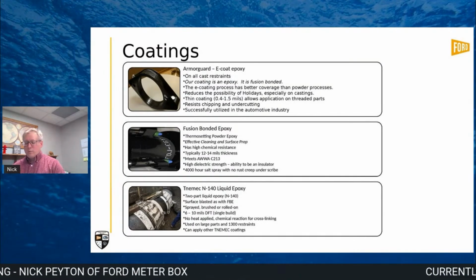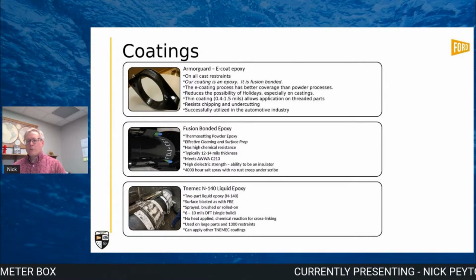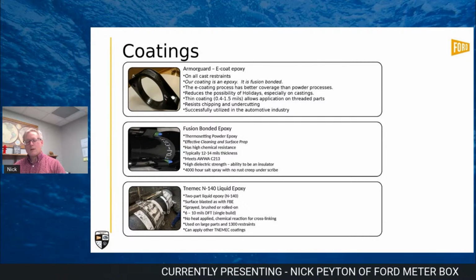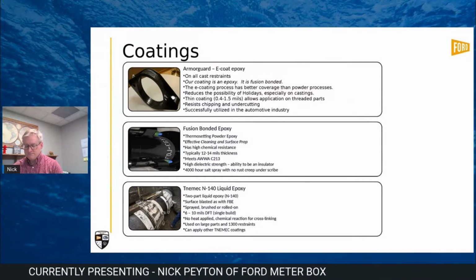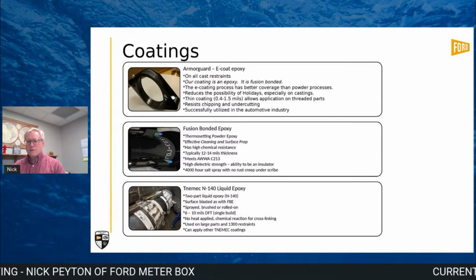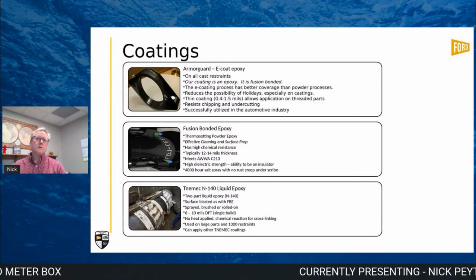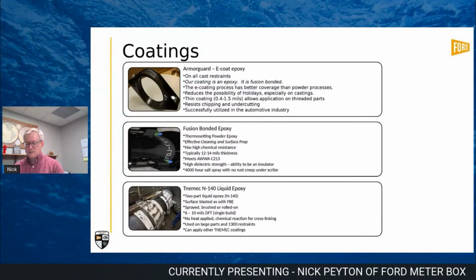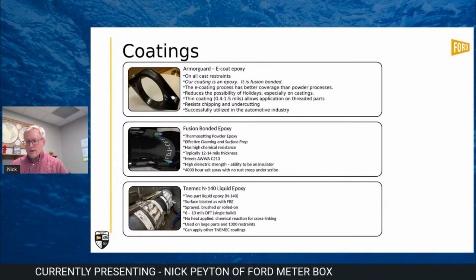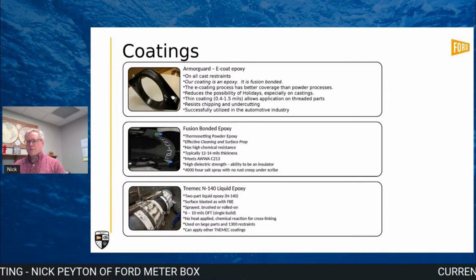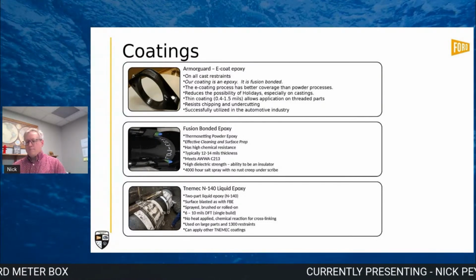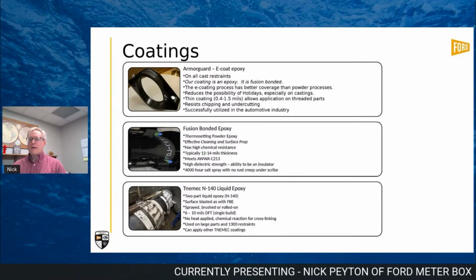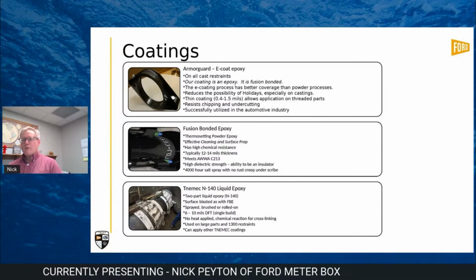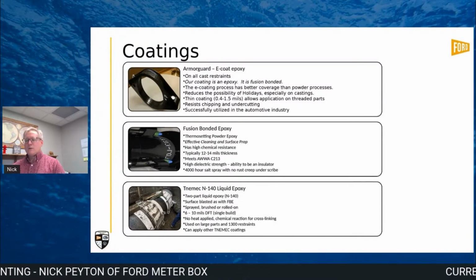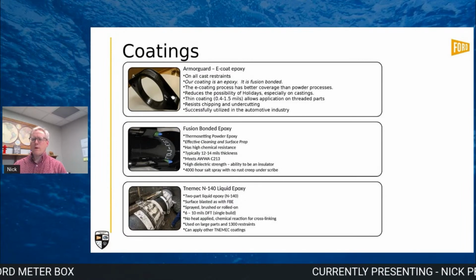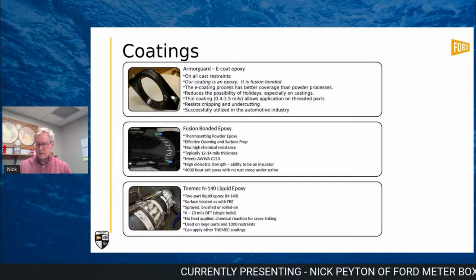Then the last and probably most popular is our two-part liquid epoxy. In this case, we use a Tnemec brand N140. And our surface preparation on the castings and the materials is the same as what you would do for a fusion bonded epoxy. Again, you have to blast and you have to prepare your casting for the coating. Surface preparation, again, is key. One of the advantages is not having to heat the casting up, but also some of the overcoat ability that you get in the two-part liquid epoxy, which are often a must and a requirement in in-plant applications.